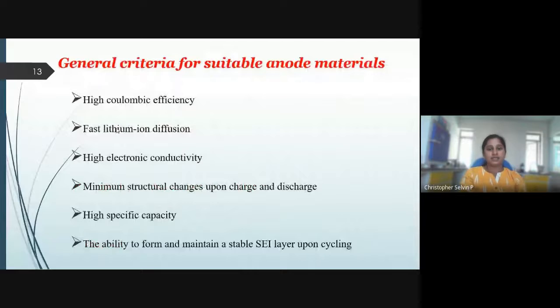The general criteria for a material to act as anode in lithium-ion batteries are: it should possess high Coulombic efficiency, fast lithium-ion diffusion, high electronic conductivity, minimum structural changes upon charge and discharge process, so that we can expect a long cycle life without any capacity fading, high specific capacity, and the ability to form and maintain a stable solid electrolyte interface layer upon cycling.